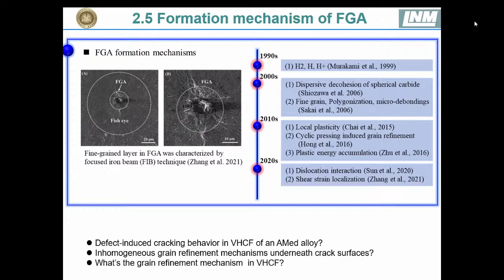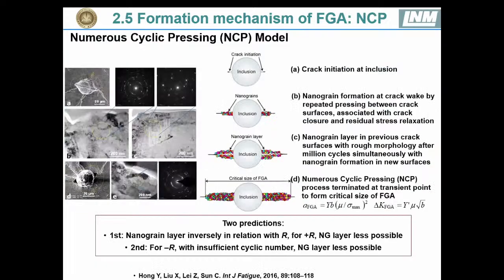However, for these additive manufactured materials, what is the mechanism, and what is the grain refinement mechanism in very high cycle fatigue? And then we come to this crack initiation mechanism. According to this numerous cyclic pressing model, it assumes that the crack initiates, and then the crack surfaces contact, and the compressive stress due to the cyclic loading will, after some amount of loading, make the grain refinement. And this is now already validated by some experimental observations.